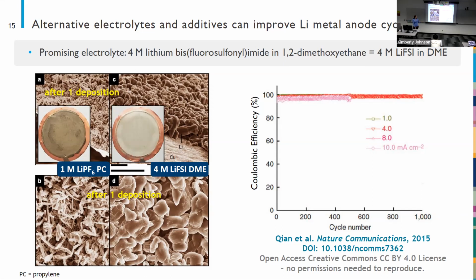This is some work from PNNL that came out about 7 years ago. It's a really beautiful paper where they use this electrolyte to show that you can deposit and strip lithium very efficiently. The Coulombic efficiency is high, and you get this very nice nodular morphology that does not look dendritic or very mossy. So this was really nice work, and it sort of started this whole branch of research into electrolytes for lithium metal that are based on high concentration electrolytes.